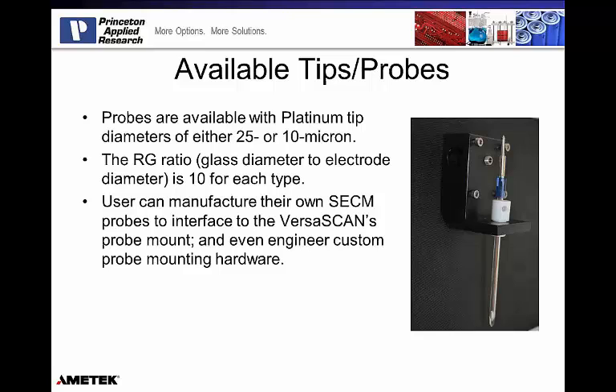So here's an example. Here's a picture of a real-world SECM tip or SECM probe. They're commercially available, typically with diameters ranging between 10 and 25 microns. These can be platinum or any other kind of noble material that is electrochemically active and well characterized. So platinum is a very good choice for this. When you're discussing SECM probes and SECM tips, you're going to come across a key parameter called the RG ratio. It's the ratio between the glass diameter and electrode diameter for the probe itself.